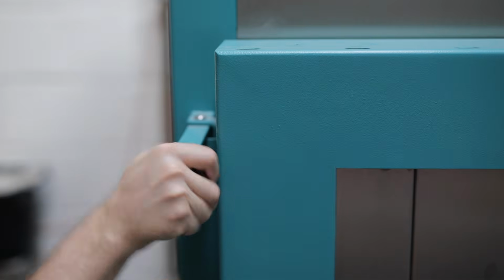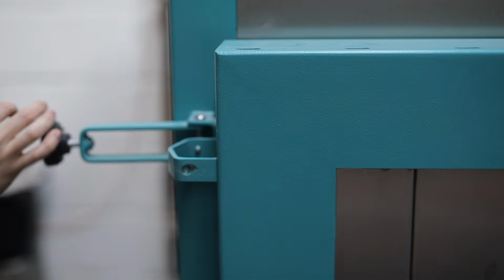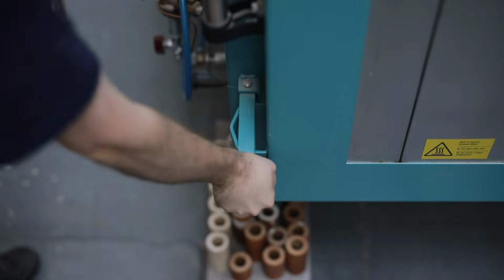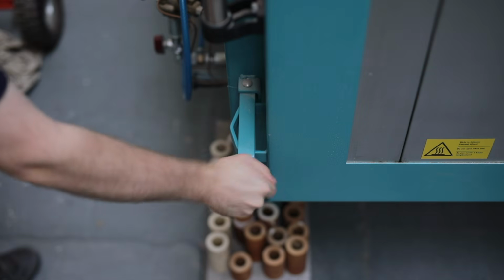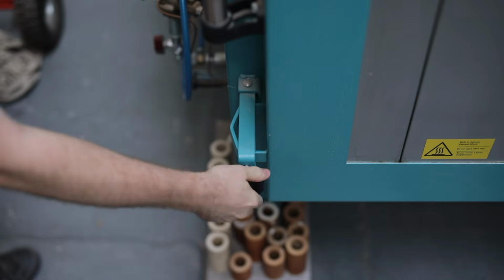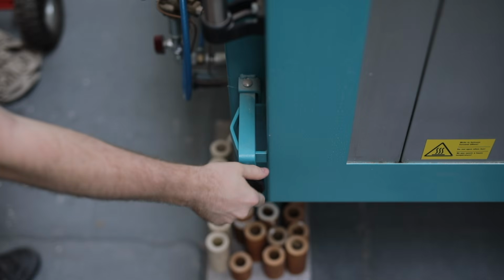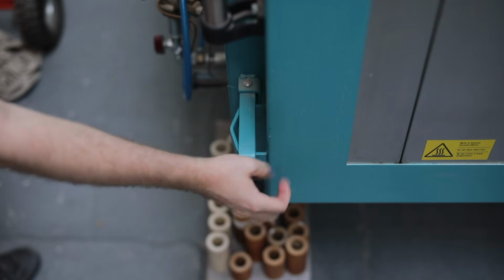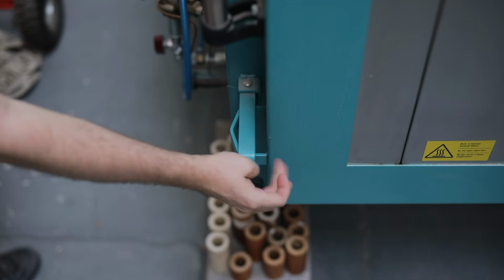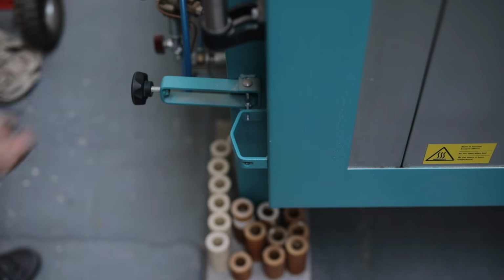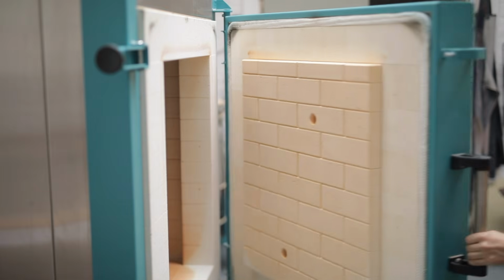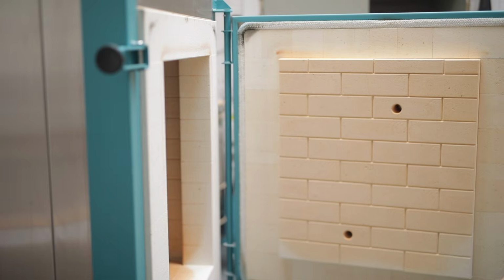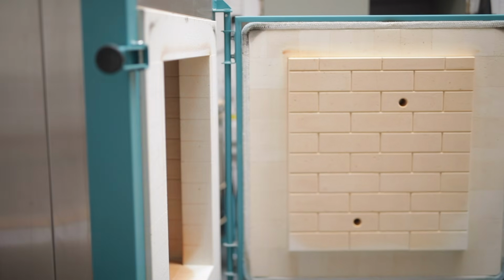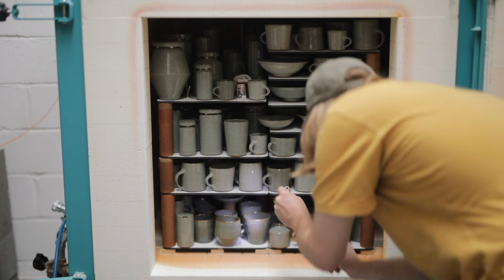This is now a few days later. The kiln has cooled all the way down to 150 degrees Celsius, and at this point I can crack the door open. This is always a very anxious moment, as really, you haven't been able to see anything happening inside this entire time. The pots are locked away and bathed in flames, and it's only at this moment that you find out whether everything went according to plan or not.